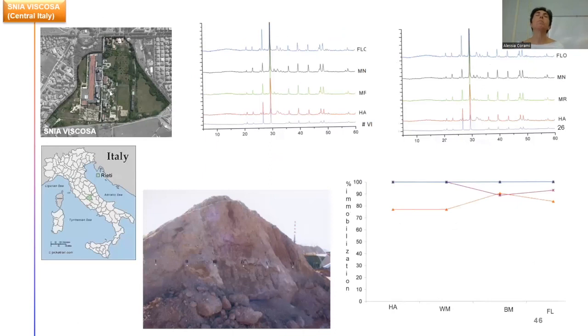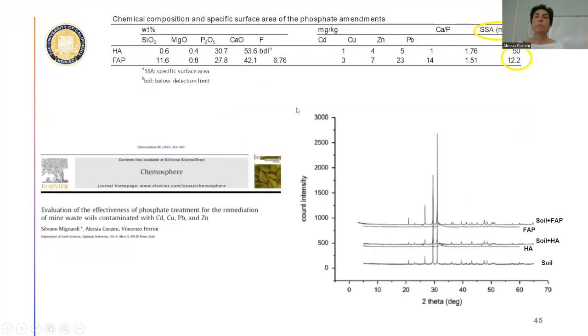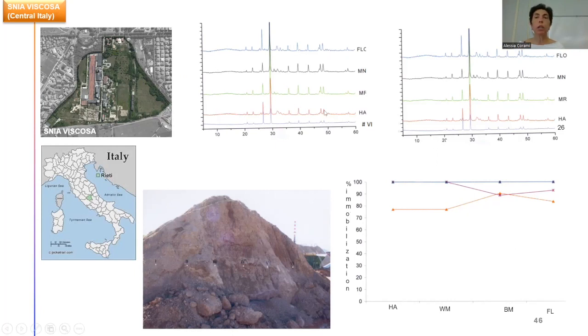Then we applied this phosphate in an in situ case. In this case, we are in central Italy. The company is SNIA Viscosa. They produced rayon. This site is closed nowadays. They don't produce anything here anymore, since the half of the past century. And we sampled these materials, which are enriched also with other contaminants. So again, we used the phosphate that we used before, and also we used the white Moroccan fluorapatite, always with the same behavior. So also from XRD, we have this shape, the same peaks, and also from analyzing the supernatants, we have a good result.